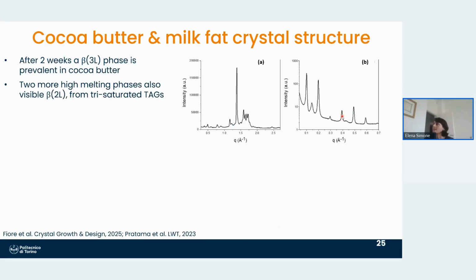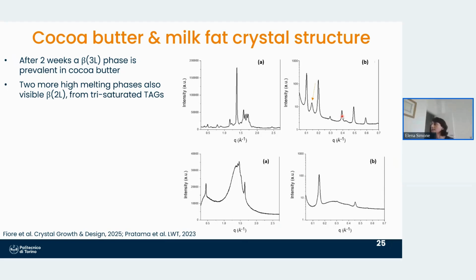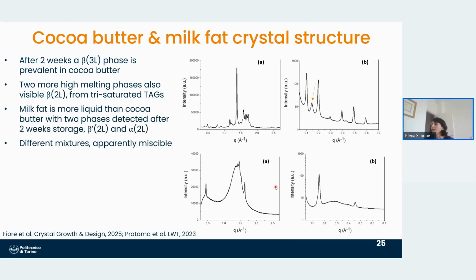These are again examples of cocoa butter and milk fat. Cocoa butter at equilibrium has a beta polymorph in a 3L form, but we can see here an extra phase, which means that there is another phase. This is probably very saturated triglycerides, which are separating from the main polymorph. Milk fat is characterized by a beta prime and an alpha mixture, and as you can see, the solid fat content is a lot lower. So we have this broad scattering peak, which is related to the presence of liquid TAGs.